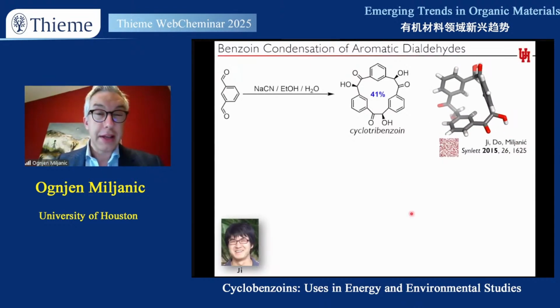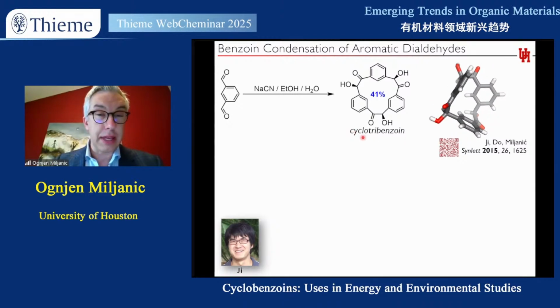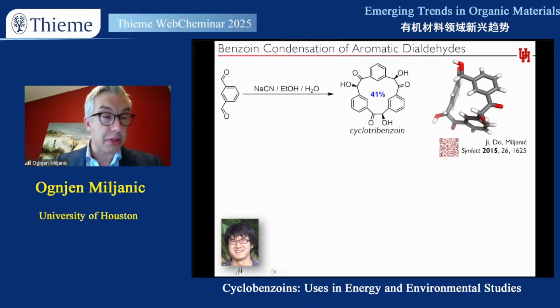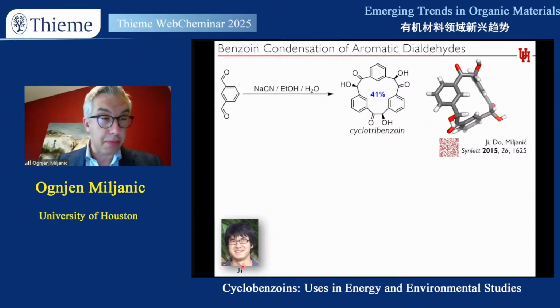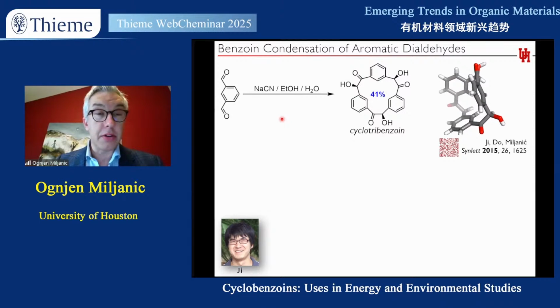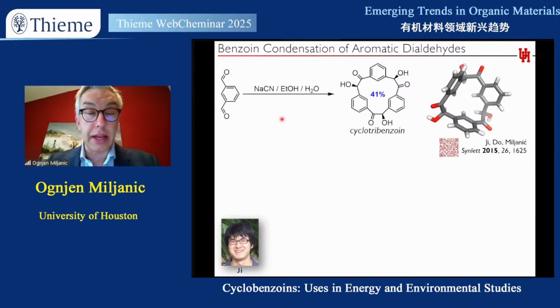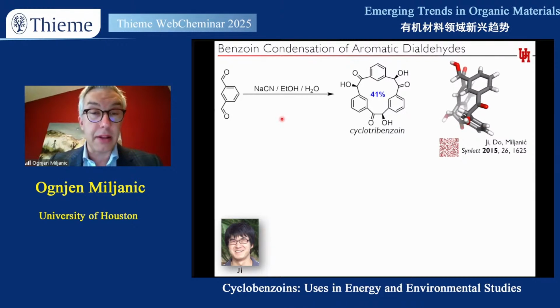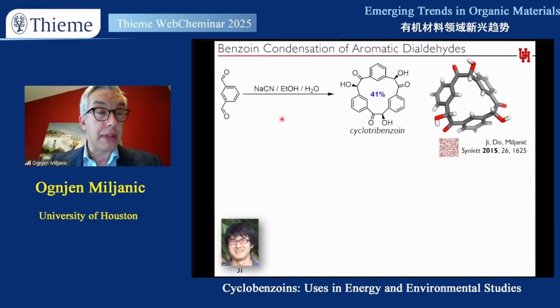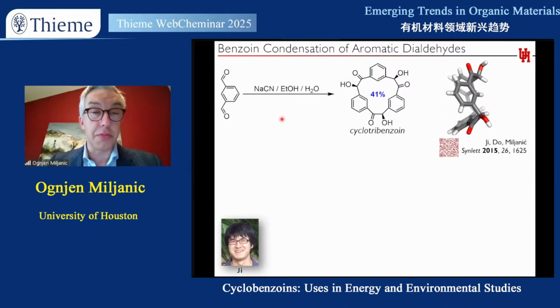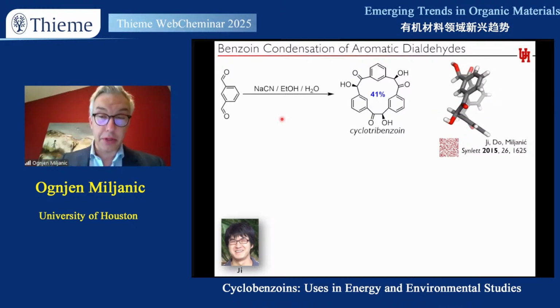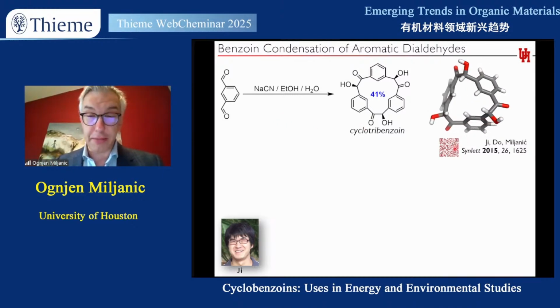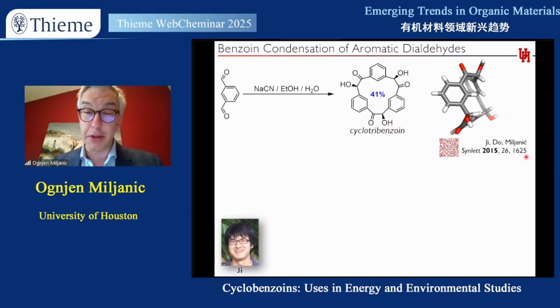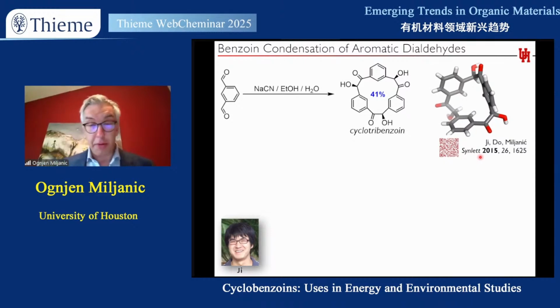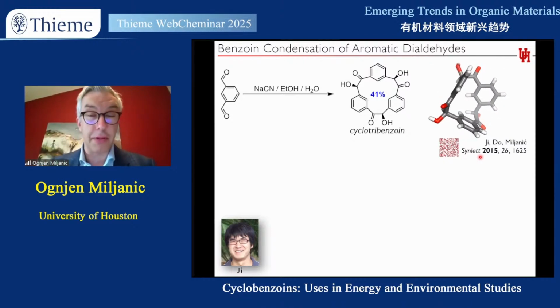chemistry and organic materials, cyclobenzoins are simple molecules that have for the first time been prepared by my graduate student Qing Ji, who is now a professor in China, by the benzoin condensation, so an extremely old, well-documented reaction that was discovered by Liebig himself, of in this case isophthalaldehyde, which in the presence of sodium cyanide, very simple catalyst, condenses into this molecule called cyclotribenzoin, which we would have published in Organic Materials, but Organic Materials didn't exist back then, so we published it in another Thieme journal, Synlett, which was for a long time headed by my PhD advisor, Peter Vollhardt.